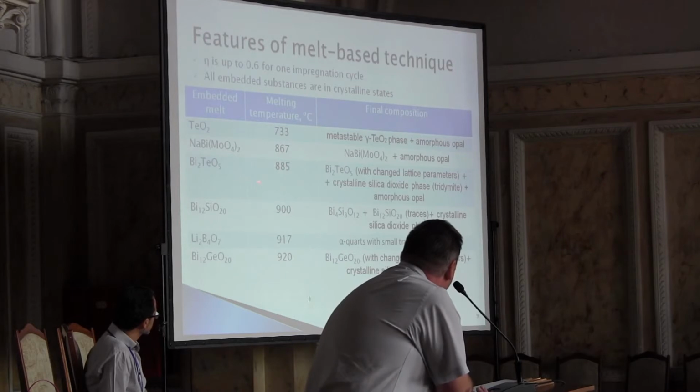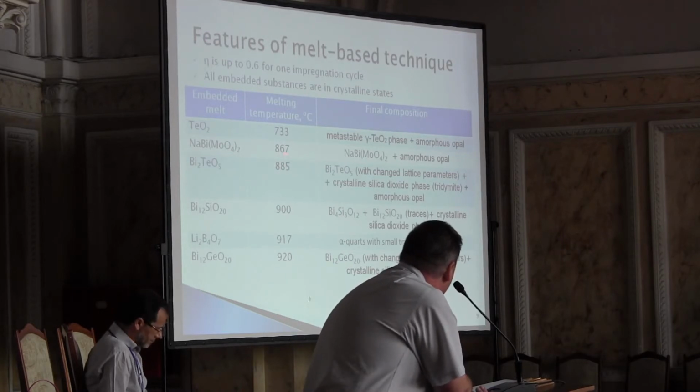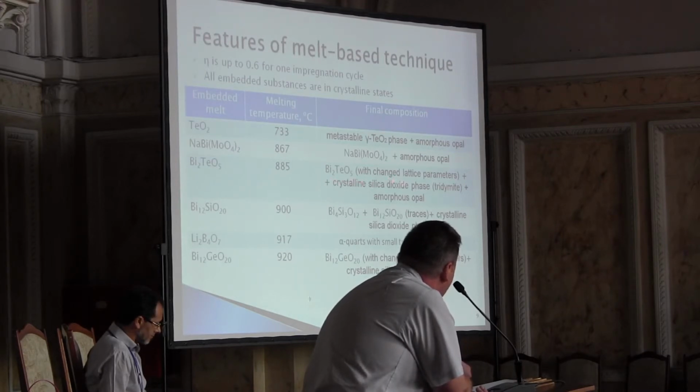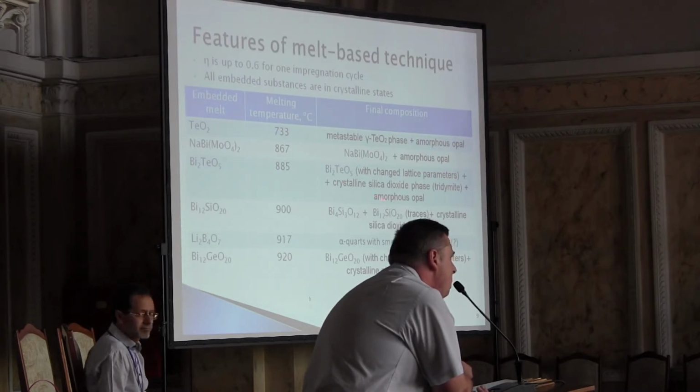Well, when we have higher temperature, we have obvious changing of lattice parameters of the embedded substance. And we have some crystallization process of the silicon dioxide matrix.